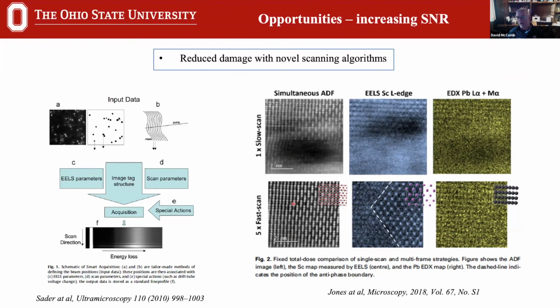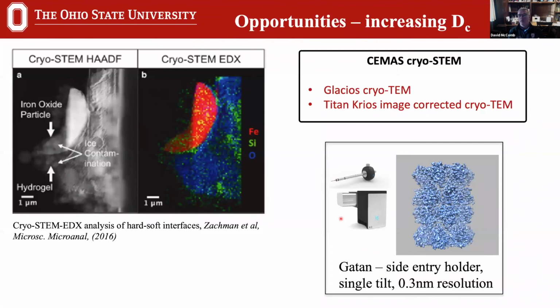But using a fast scan and then what Lewis calls a smart align approach, we can actually now start to acquire more quickly. We take fast scans and then add the data together without the noise amplification that we would normally see with that. And now we can get to much better approaches. And so we've installed this smart align system currently on the Titan Themis, and Binbin Wang and Naria Bagwez are looking at this to see how we can actually exploit this. And then the one tool that we have left at our disposal to increase the tolerance to dose is to actually go to low temperature.